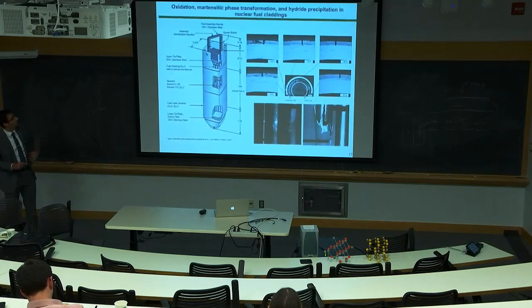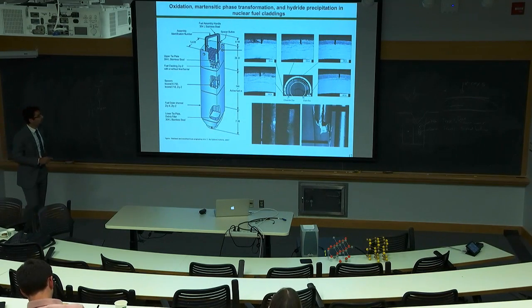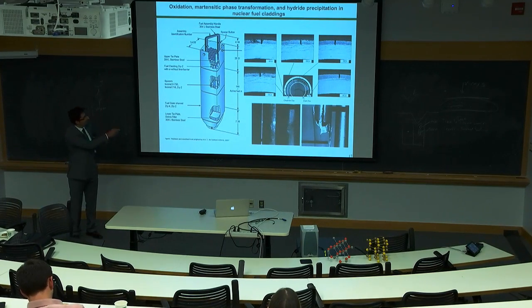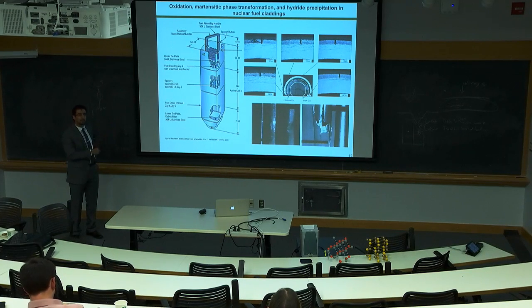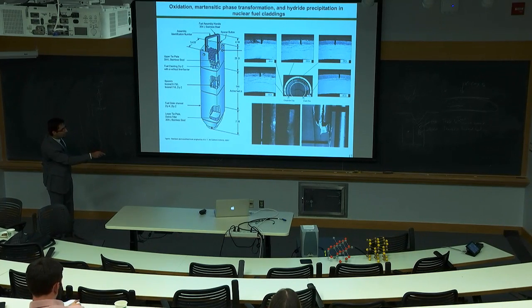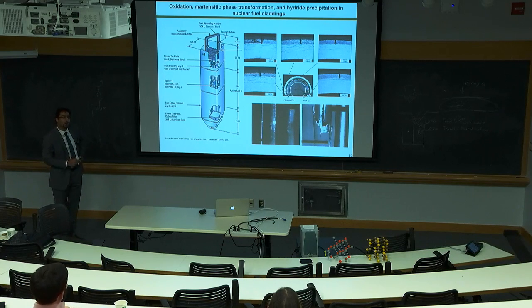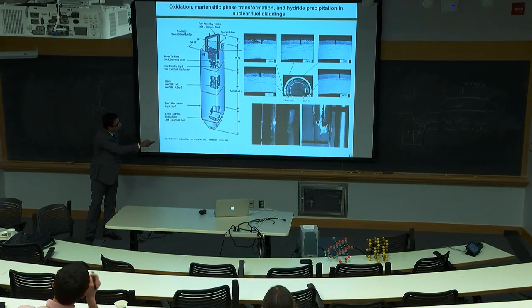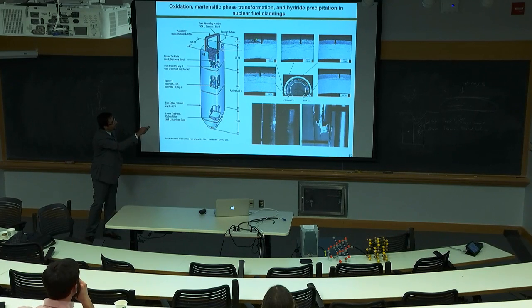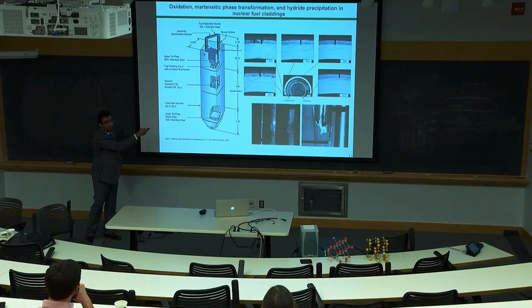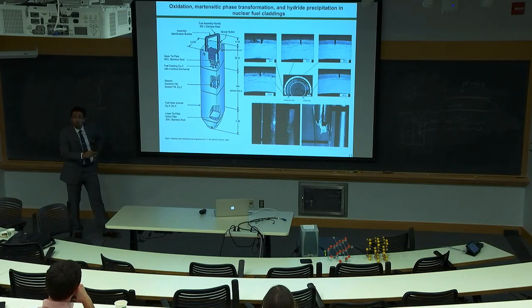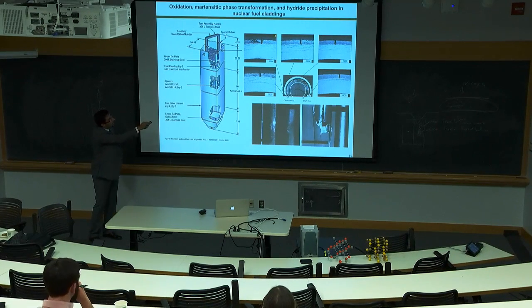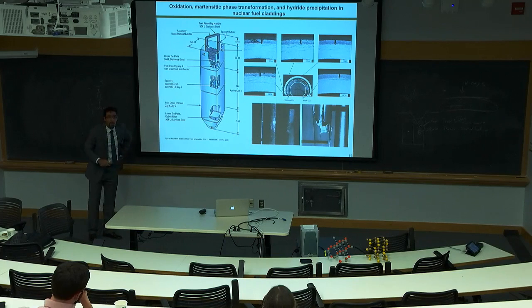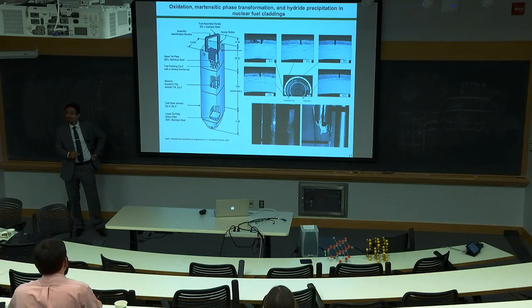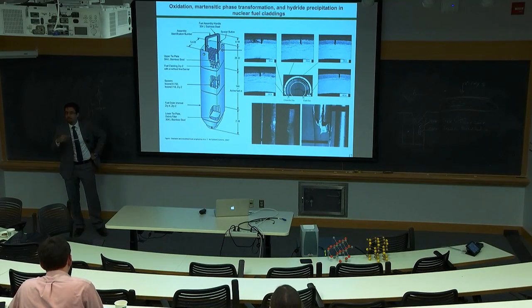Let's go to nuclear reactors. This is the assembly of nuclear fuel rods, and this is a failed nuclear fuel rod. You're looking at the surface of this failed rod. You see the crack here. You see lots of these small lines in this direction; they are hydride precipitates. This layer here, dark gray, is zirconium oxide. It's called zirconia.